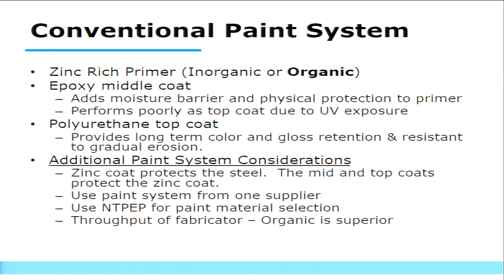So we definitely recommend to all the owners in the room and anybody looking to specify the paint system to go to NTPEP. And then finally, the throughput of the fabricator. I mentioned organic is superior, and I highlighted it up here. Generally, fabricators would prefer organic zinc-rich primer to inorganic zinc-rich primer. And that has to do with the environment and the curing rates for organic versus inorganic.